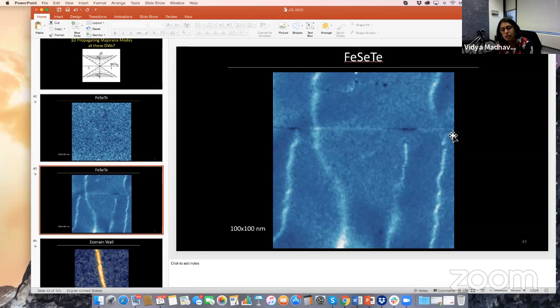This line is also a domain wall of some kind. These two are probably a grain boundary, actually. If you have a dramatic grain boundary, what we find is that on step edges and grain boundaries, we often see in-gap states. Sometimes we can find Y junctions where you have three domain walls meeting, and at the Y junction, we actually see a zero bias peak. So it's really interesting.